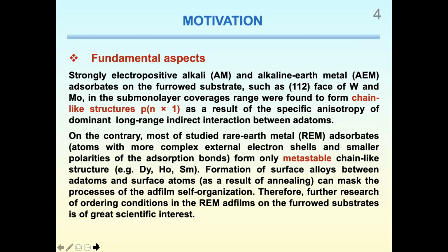The chain-like structures of the 3 other systems turned out to be metastable. They lost the long-range order after annealing at some higher temperature and subsequent cooling to lower temperature. It was suggested that such an operation results in formation of a surface alloy between adatoms and surface atoms, which solidifies as a surface glass due to the fast decrease of atom mobility with temperature. This can actually mask the processes of adfilm self-organization and motivates further research of ordering conditions in rare earth metal adfilms on the furrowed substrates.